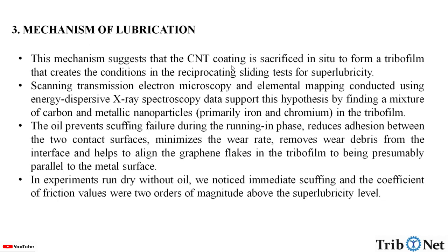The mechanism suggests that the CNT coating is sacrificed in situ to form a tribofilm that creates the condition in reciprocating sliding tests for superlubricity. Scanning transmission electron microscopy and elemental mapping conducted using energy dispersive X-ray spectroscopy data supported this hypothesis by finding a mixture of carbon and metallic nanoparticles, primarily iron and chromium, in the tribofilm.